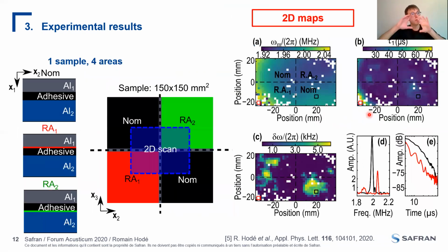So that was for when we have 5 different samples with 5 different treatments. But now we are interested in what will happen when we have one sample and 4 different areas in the same sample, and to do an image of the bonding. So here you have the sample, with 2 nominal areas and 2 degraded areas. And we have made a 2D scan with this laser ultrasonic technique based on the attenuation of the ZGV mode, and we have identified the different parameters.